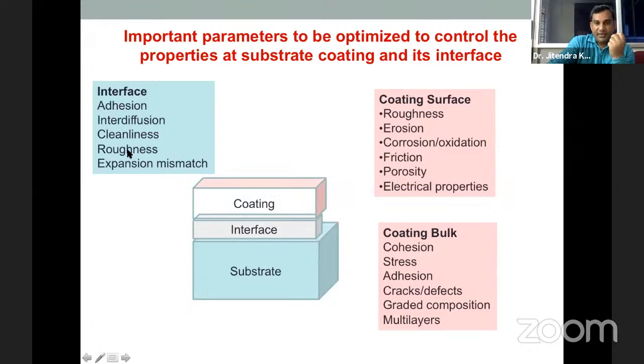Interface means in between, we just check the adhesion. So this adhesion, the interface between these two coatings, we can check by the pull-off force. That pull-off force we can also generate by using atomic force microscopy. So we just apply a very heavy load over the surface, because these coatings are 10 nanometer or 20 nanometer, then it can stretch out. So at what load your coating can be detached from the surface, that is called pull-off force analysis by using atomic force microscopy.